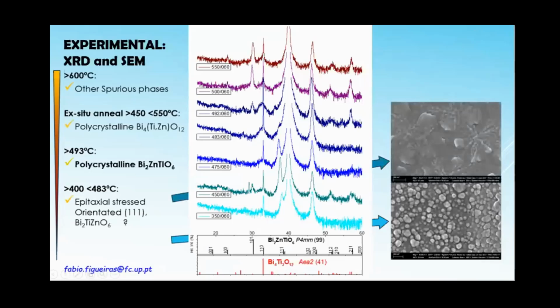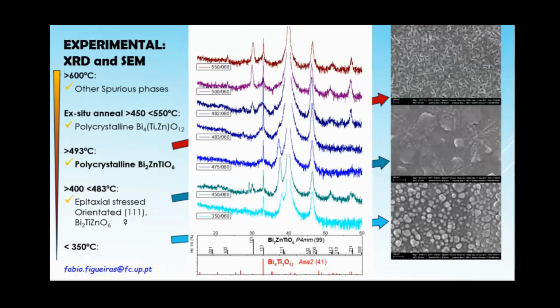And what we got is that the material at low temperature is almost amorphous. The material at medium temperature will start to form the film in an epitaxial way, but it still has much amorphous and double other phases. So let's try to anneal this material, and it turns out to be another oxide, bismuth 4 phase. And we have a very narrow window between 500 degrees C and 550 that can really make this phase stabilize. And so you can imagine that we made lots of samples and lots of substrates until we found the right conditions to check this material.